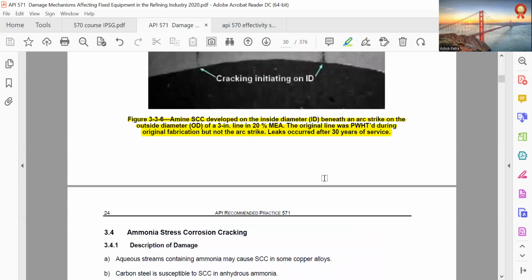Cracking initiated on the ID because the process side amine SCC developed on the inside diameter, ID, beneath the arc strike on the outside diameter, OD, of a 3-inch line in 20% MEA. The original line was PWHT during the original fabrication but not the arc strike. Leaks occurred after 30 years of service.